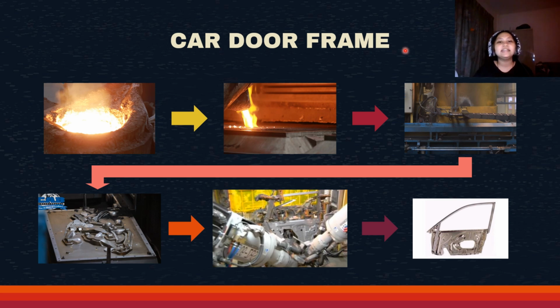Before starting the casting process, the die casting machine goes through the clamping process, where the die halves' faces are cleaned and applied with ejection lubrication or release agent. The die halves are then closed and clamped together with pressure applied from the die cast machine. The molten aluminum, as you can see in the first picture, is maintained at a temperature of 660.32 degrees Celsius and then transferred into an injection chamber, as you can see in the second picture, and injected into the closed die prepared just now.